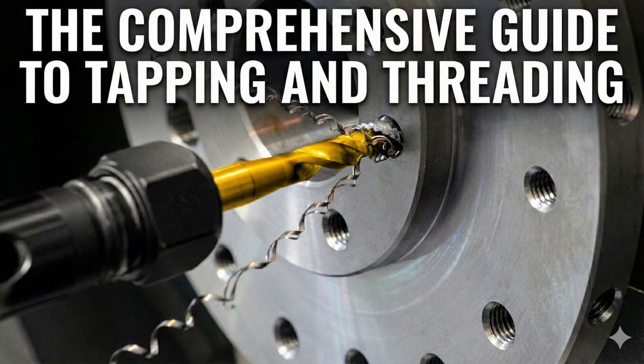Exactly. Because the forming process compresses the metal, it actually creates a denser, tougher thread structure that is often 10 to 30% stronger than a cut thread in the same material. And you get a better surface finish, too. A much better, smoother surface finish. Since there are no chips, there are no thermal issues tied to chip removal or friction. And the quality and longevity of a formed thread in a ductile material just far surpass that of a cut thread. It really is a high-performance solution, even if the machine has to work a little harder to get there.